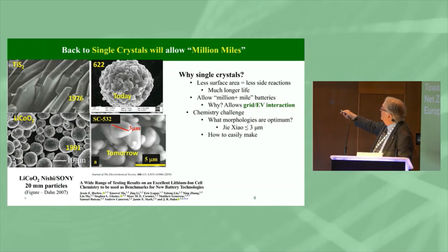The other thing it also prevents, you see here, all our primary particles are jammed up against one another. These particles expand and contract about 10% on cycling. So these meatballs tend to crack. If you have single crystals, then they're not connected to each other. They can freely expand and you shouldn't get cracking. And cracking is what gives us capacity fade. And again, my ex-student Jie Xiao has shown that if you have these single crystals, keep them 2 to 5 microns in size, they themselves do not crack as you expand and contract them. So this is really where a lot of the effort is going now.